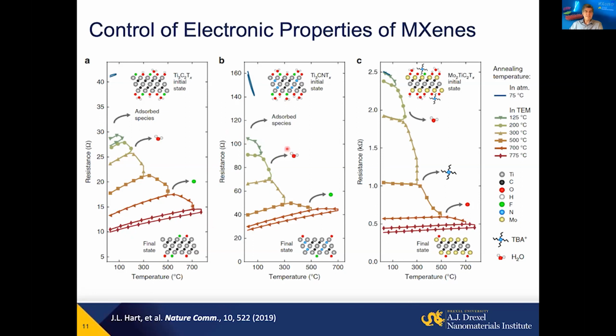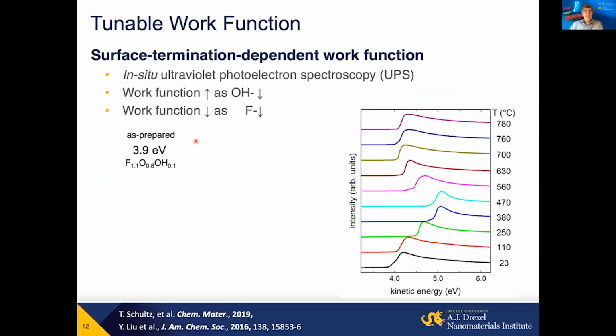from semiconductor-like behavior, so resistance increasing with decreasing temperature, to metal-like behavior by simply removing surface termination, removing intercalated species from those materials. And in a very similar way, we can change the work function in these materials.